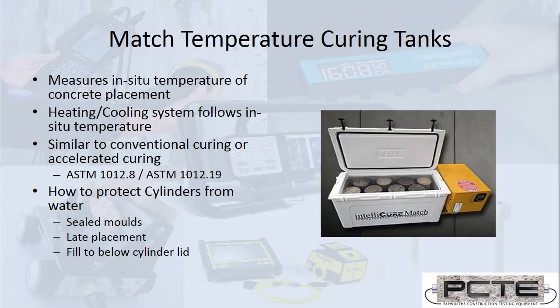Now, another technique that I have seen used is where there are cores taken from the element after it's sort of gone through initial curing, or where plastic cylinder molds are placed inside that element and can then be popped out to give a ready-to-go cylinder heated by the concrete around it. Match temperature curing tanks instead try to capture the concrete's heat in an external environment. A temperature sensor is placed in the concrete, and whenever we're using a temperature sensor as a tool to assist us with early age strength, the placement of that temperature sensor is important. If there's a critical area where stresses are going to be greatest in the structure, it's important that the sensor be placed to capture the strength gain of that area.